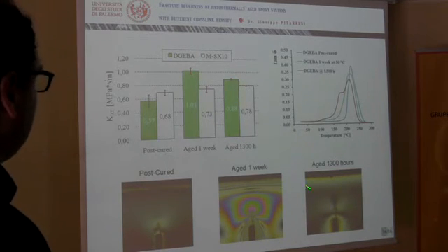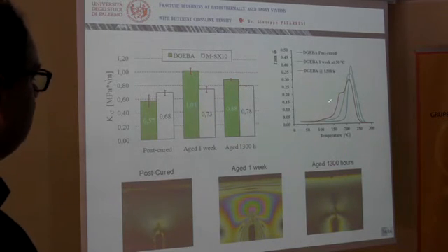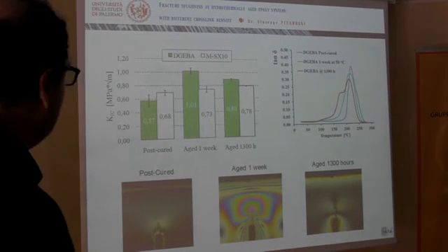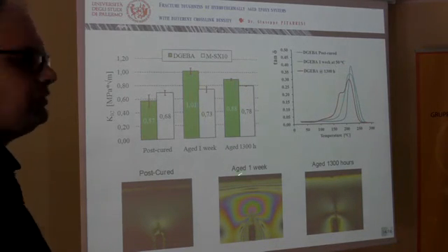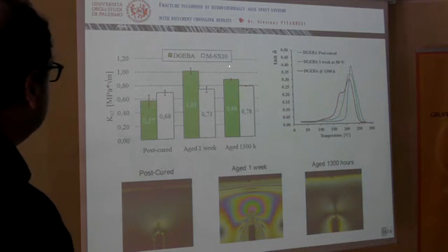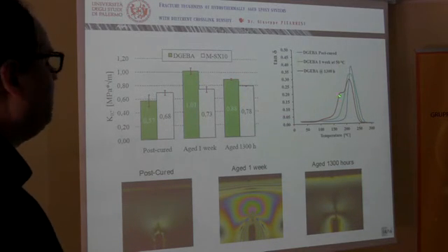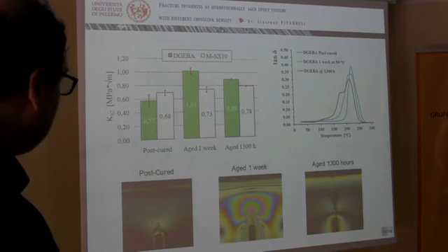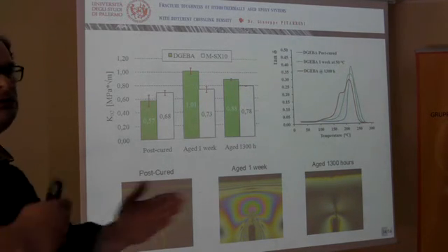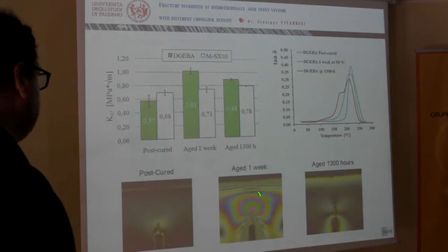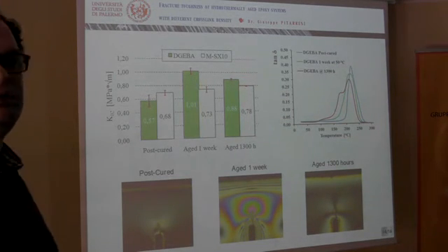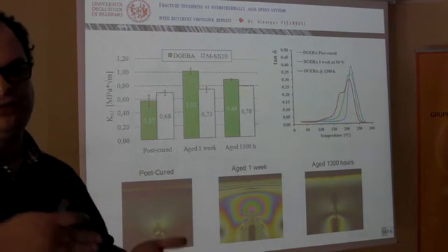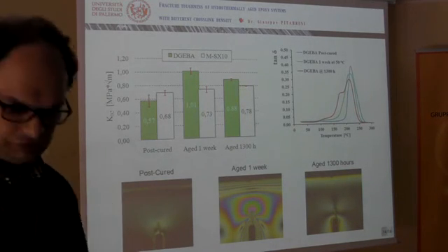The fracture toughness measured at saturation, which means when there is again a stress-free situation, indicates an increase of fracture toughness. And we explain this final increase as an effect of the plasticization induced by the water penetration. But of course, in order to decouple the influence of the stress and the influence of the plasticization, photoelasticity was very effective in guiding us to these conclusions.